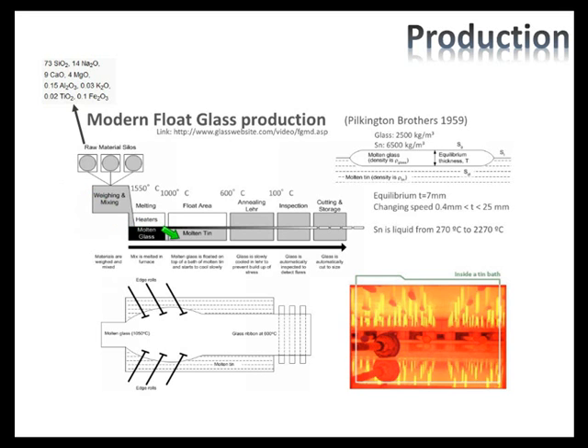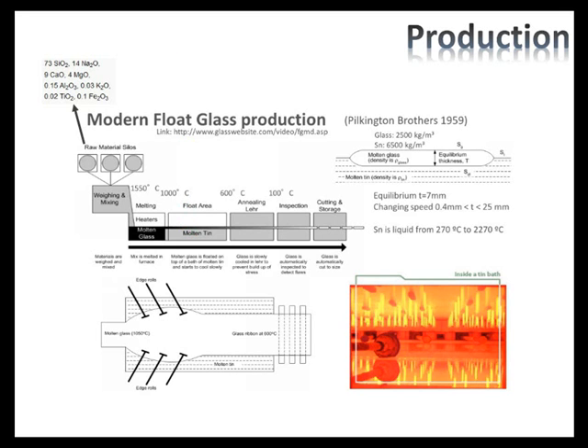That float line consists of some type of molten material — it's often molten tin, though sometimes other elements are included. The heated glass material floats up on top of that more dense material, forming the base. The glass comes to a natural thickness when poured onto the molten tin, and that material can then be pushed out or in to change the overall thickness. When the glass comes off the line and cools down, that is how we end up with formed glass off of a float line. This process — where there is an air side above the tin and a side of the glass on the tin — is important for how glass behaves as a material.